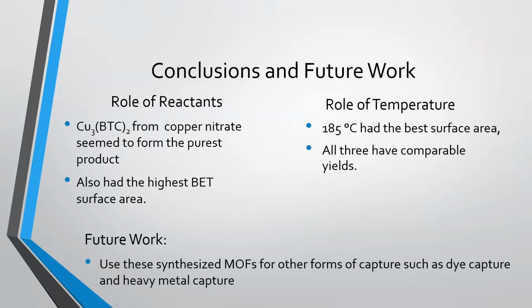After this, we concluded that our copper BTC from copper nitrate seemed to create our purest product with the highest BET and surface area, as well as comparable pore volumes. As far as our temperatures were concerned, we found that 185 degrees had the best surface area, while all 3 had comparable yields.